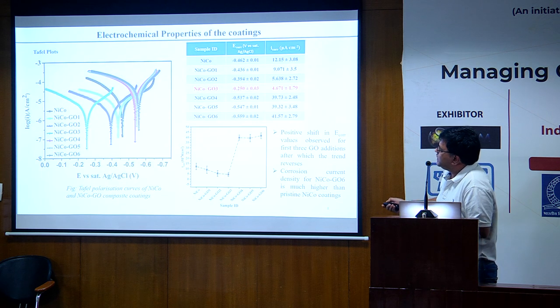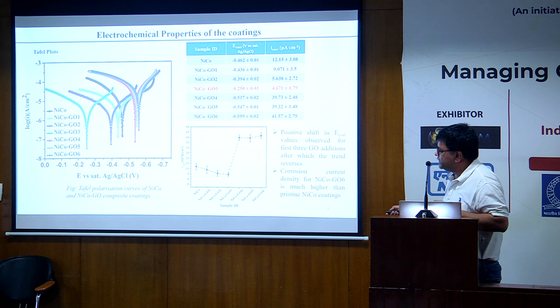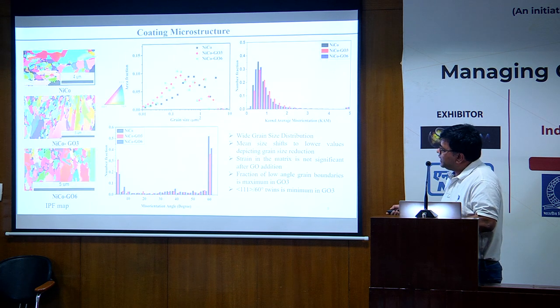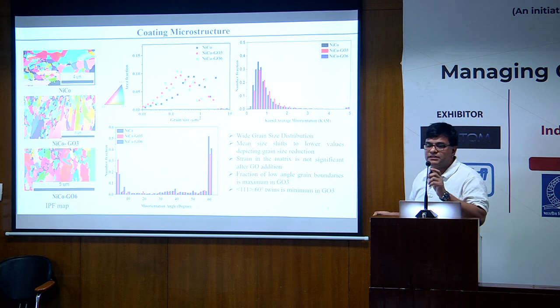But we see that the I-corr value has a drop. So basically, this is for the nickel cobalt coating. And if you keep increasing the amount of graphene oxide, the value drops till here, and then there is a sudden increase. So what we wanted to see is why is this drop happening here? And we did some texture-related studies.